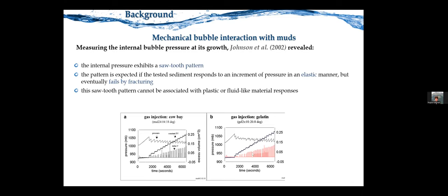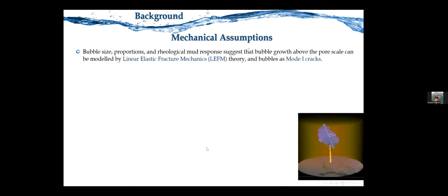And as such, the mechanical assumption of this theory of bubble growth is the following. The bubble size proportions and rheological mud response suggest that bubble growth follows elastic fracture mechanics theory, and the bubbles themselves, which you can see here, big bubbles even compared to the size of the core where they are injected, behave as mode one cracks.